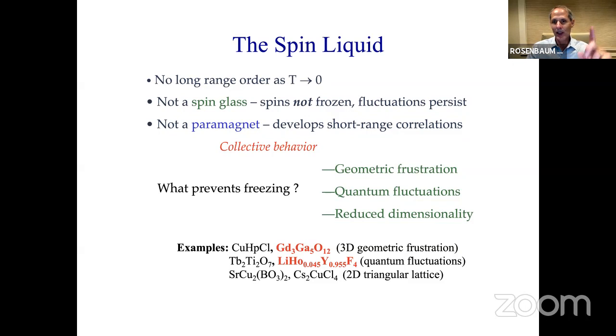Their origin is that if you think of the dipolar interaction, if I have a concentrated sample, then the transverse component of the dipolar interaction, remember the dipolar interaction looks like a butterfly, cancels in the concentrated case. So if I have a spin here, its transverse component is canceled by the spin on the other side. However, if I now dilute it, I wind up with many spins that do not have compensation. So I have effectively an internal transverse field of order kilogauss that gives you, just by dint of disorder, the quantum fluctuations. And it's not a simple paramagnet because there are short range correlations in this material. So you get collective behavior.